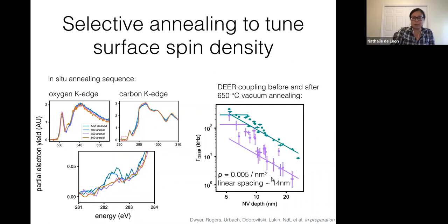So the first big puzzle is that if you just extract the naive model for what the density of surface spins is, given this set of purple points here, this corresponds to around 0.005 spins per square nanometer, which is a linear spacing of around 14 nanometers. So this means that the surface spin to surface spin distance is now comparable to or much larger than the NV depths that we're looking at.